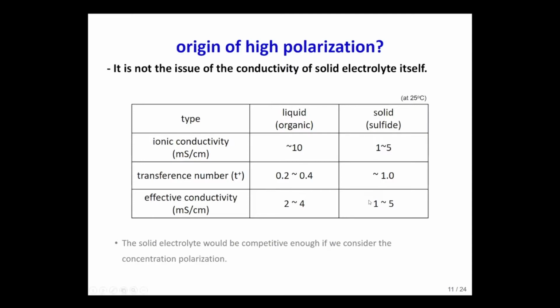On the other hand, the conductivity of a sulfide-based solid electrolyte, such as argyrodite, is at least 2 millisiemens per centimeter or higher. And the transference number in this case is close to unity. Then the effective conductivity would be more or less the same as that of liquid electrolyte. Moreover, if we consider the concentration polarization, the actual lithium-ion conduction should be faster in the case of solid electrolyte. Overall, we cannot say that low lithium-ion conductivity of solid electrolyte is responsible for the unsatisfactory rate performance of solid-state batteries.